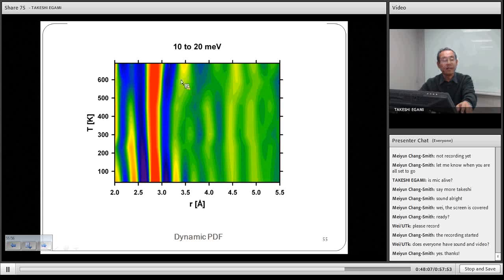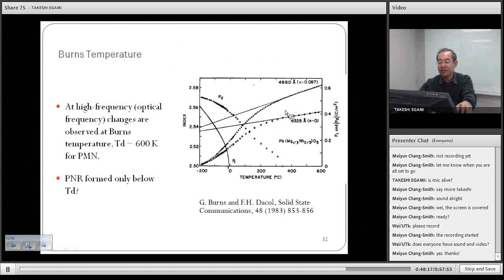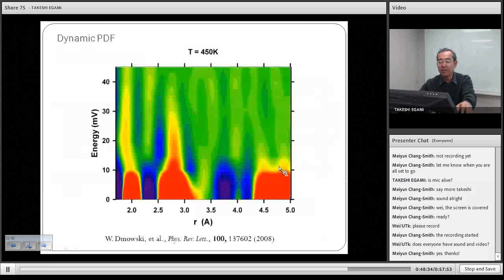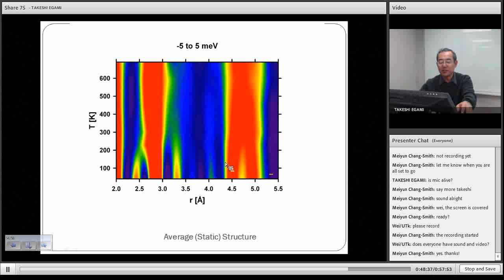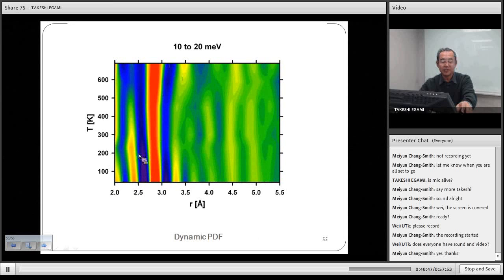So this shows you this. There's a dynamic polarization up to 600 Kelvin. Okay, so this again corresponds to this temperature. So up to this temperature, some kind of response is there, and then optical response is there. Something is happening even though there's no real ferroelectricity, and that is because there are local dynamic polarizations. The static polarization disappears at room temperature and nothing above, but dynamic polarization persists up to temperatures as high as 600 Kelvin.